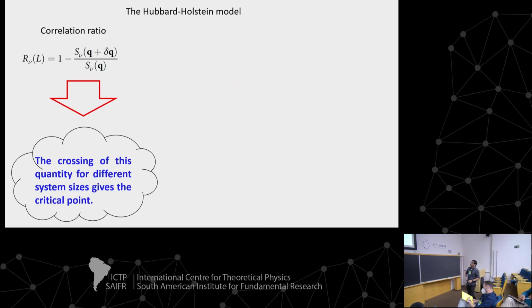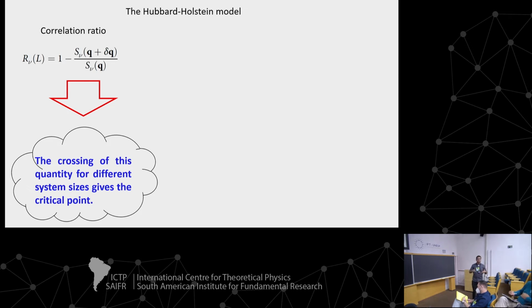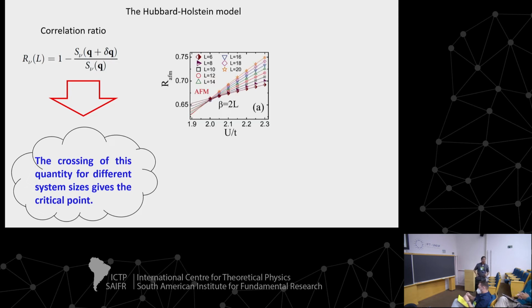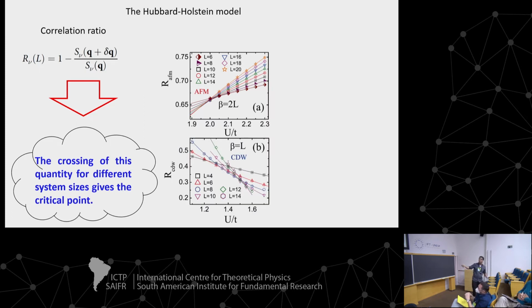Okay, so this is my first goal here, trying to build this phase diagram for the Hubbard-Holstein model at the square lattice first. In order to do this, I have to define one quantity, this is something technical, sorry, that I call the correlation ratio. This is something proportional to the correlation length. And we use this as something similar to the Binder cumulants if someone does Monte Carlo. So basically, the crossing of this quantity gives us the critical point. So we have analyzed this, starting with very large values of U and decreasing the values of U. And the crossing of this quantity gives us the critical point. So we have indeed a magnetic critical point here for a given value of U. If we do the opposite, for instance, starting with large values of electron-phonon interaction, we also have the same crossing, but the crossing here is not as beautiful as this one here. But we also have the crossing, and we can define the critical point.